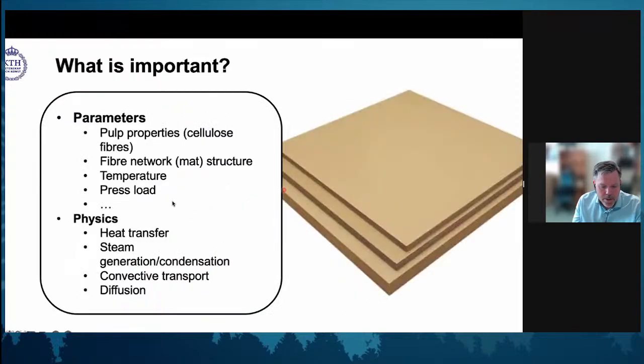So to try to understand this, we start by thinking about what was important. Of course, you have pulp properties that always tend to be important. So the cellulose fibers are a special type. You can't use any type of cellulose fibers. We also know that the fiber network mat that you create is of importance. Temperature when you make this material is of importance, as is the press load. And you can start to find other, maybe more insignificant, but still important parameters.